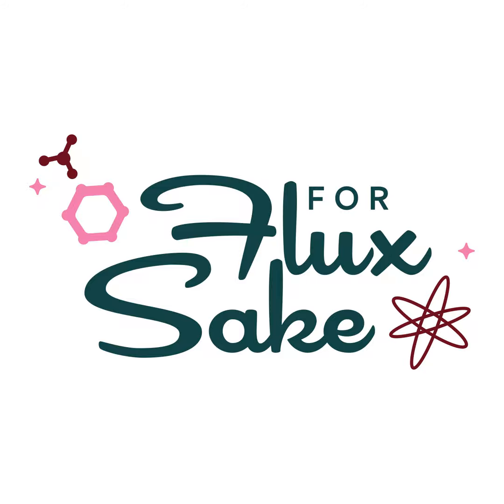And everybody's got their opinion. We put out a YouTube video not long ago, and Rosen made a comment on it about this being a perfect glaze, and somebody in the comments is like, well, how can you call it perfect when it's crazing? And the answer is because it's based on the glaze and the clay body. This is why you'll see the problem where you'll have a glaze that will craze on your porcelain but not your stoneware, because those two clay bodies have different thermal expansion. Not all clay bodies have the same thermal expansion. And so on the porcelain, the difference is enough to cause it to craze, and on the stoneware, it's enough to cause it not. So you look at a glaze that crazes, don't judge the glaze. It's about the clay body it's on too.